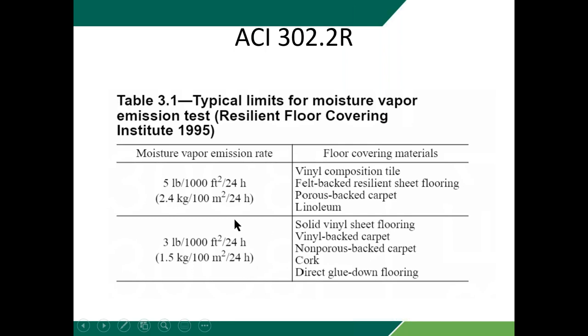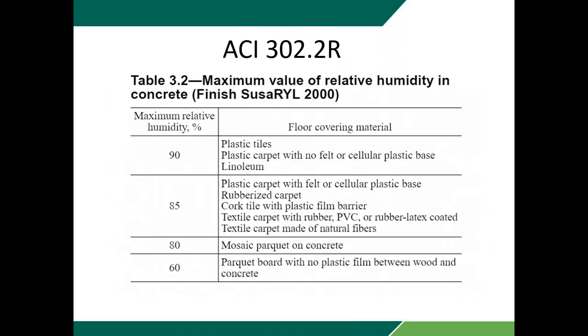And we can see here that typically we're looking for about 3 pounds per 1,000 square foot per 24 hours for moisture vapor drive. And again, we'll discuss in detail how that's measured. They also provide charts on the relative humidity, and this is actually just measuring the humidity level in the concrete itself. So typically, like I said, today I see most of my manufacturers out there calling for 70-75% relative humidity. You should actually look at whatever the manufacturer's limitations are, and that's what you should include in your specifications.